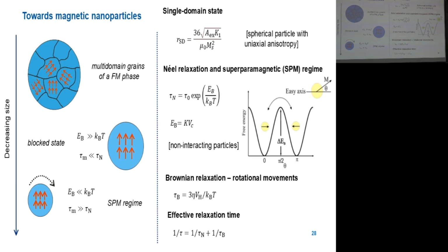However, if the particle is small enough, or if the temperature is large enough, it may easily happen that the thermal energy will overcome the energy barrier between the two orientations of the easy axis, and the thermal energy will cause the magnetic moment to rotate basically freely, or to relax, to reverse between the two orientations. And this phenomenon is typically called the Néel relaxation, and it is leading to superparamagnetism.